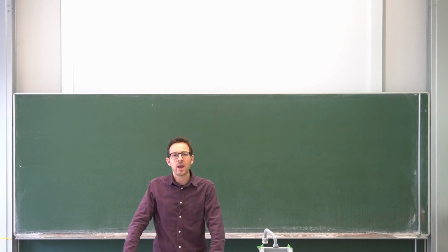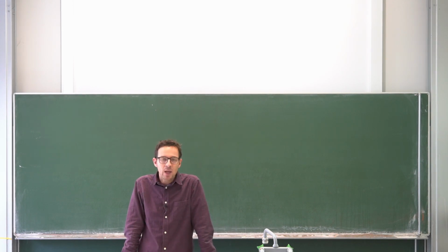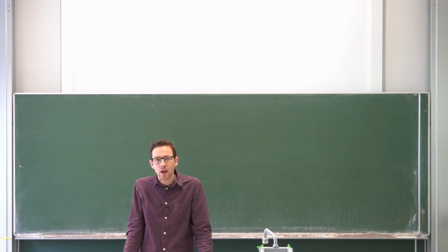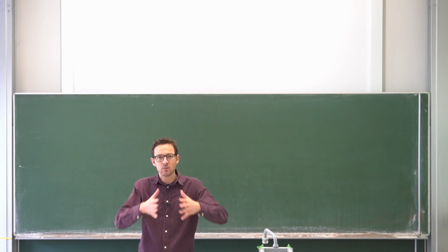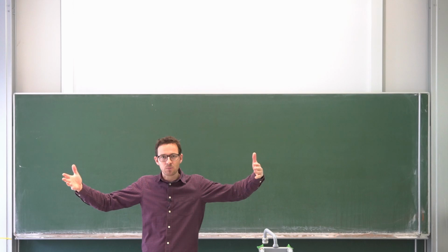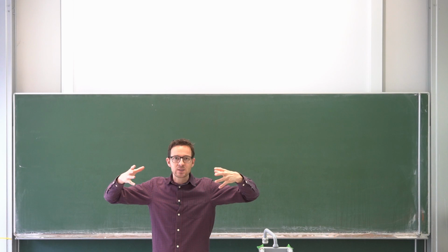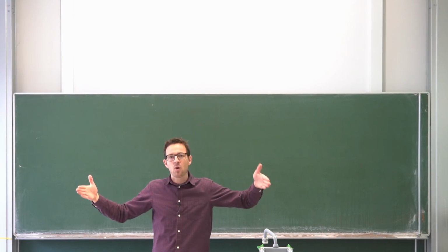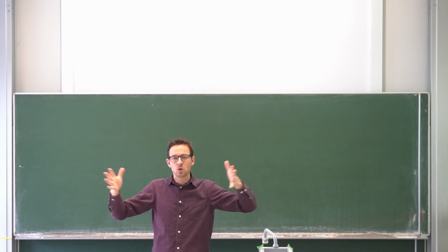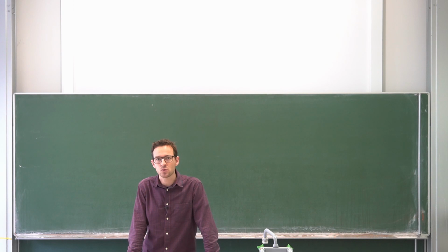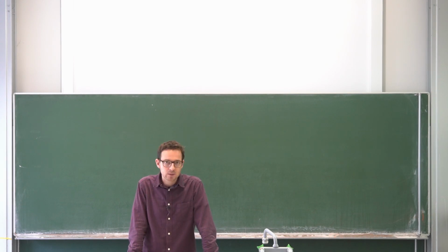So this is a very peculiar behavior because it implies that the rubber, at least under tension, has a negative thermal expansion coefficient. And intuitively, from daily life, we know that materials have a positive thermal expansion coefficient. Now, if you heat something up, it will expand in volume. And why is that? Because you supply more energy, so the bonds start to vibrate more, the molecules can pack less densely, and everything expands. While for a rubber, it seems to be the other way around. It seems to contract when you heat it up. And those are now two puzzles that we want to solve by applying thermodynamics.